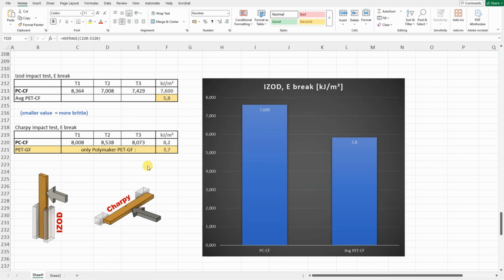On the Charpy test I don't have enough data, only one, the Polymaker PET-GF, so it is not presented on the graph. On the IZOD I have enough data even for the average PET-CF, and we can see that this PC-CF is tougher compared to the average PET-CF material, and it is more brittle compared to, let's say, ABS, but at least 2 times tougher compared to the average PETG.